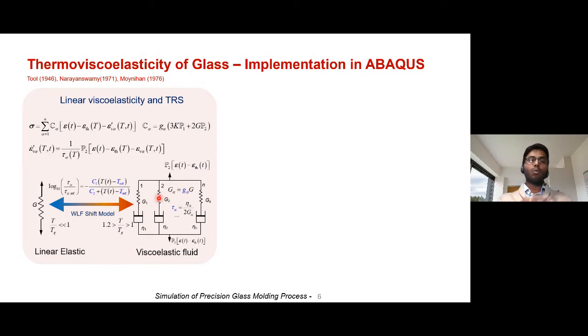But as I mentioned, at room temperature, it behaves elastic. That means the relaxation time becomes very, very large, or the viscosity of the material is very, very high at room temperature, and it is not able to relax anymore. That is why the relaxation time goes to infinity, and it has to be taken as a function of temperature. You can take a shift function which takes into account these temperature effects, transitioning the relaxation time from a finite value to an infinite value. So this is the constitutive model we use.